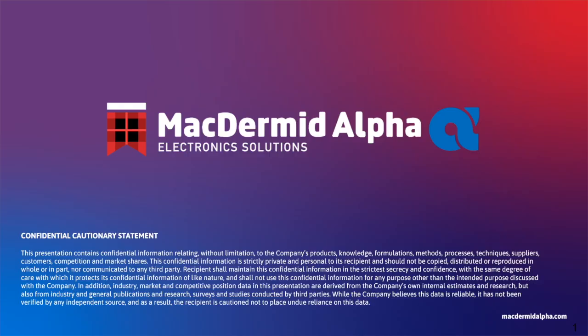In some cases, this happens when the thermal cure is triggered. So when you dispense a pattern, you may not necessarily see anything come out, but as soon as you provide heat, as a function and a combination of heat and the surface characteristics of the surface that you're depositing on, you might see materials come out. And there is an example in one of the slides of how a bleed out may look like. So we look at the bleed out both as dispensed and as cured, and both in a dispensing pattern where we probably go for anywhere from a dot to a star-shaped pattern or any other pattern that makes sense, as well as where we actually attach a die.